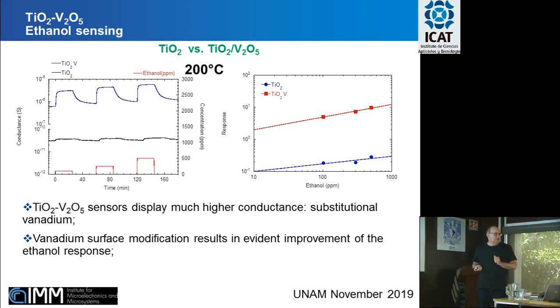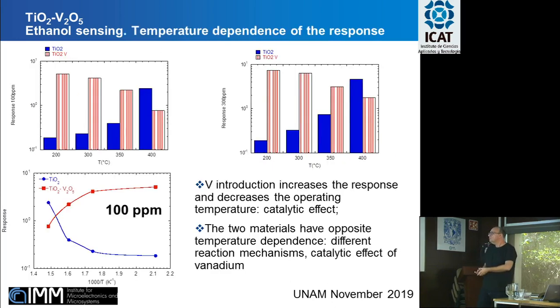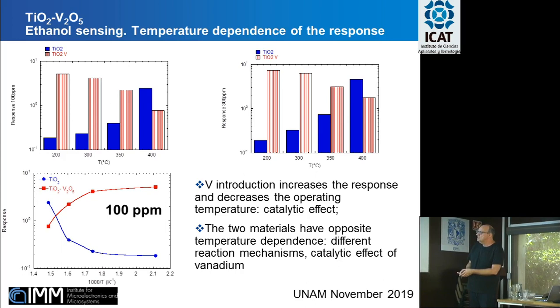And is it really working as a catalyst? It seems so. We see, for instance, that for two different ethanol concentrations, with pure titanium the response is slowly going up to 400 degrees C. We have to heat the device up to 400 degrees C. When we put vanadium onto the surface, we have exactly the reverse effect. We have the maximum response at low temperature, which is decreasing with increasing temperature. So it seems that the vanadium introduction increases the response and decreases the operating temperature, which really seems the demonstration of some kind of catalytic effect.